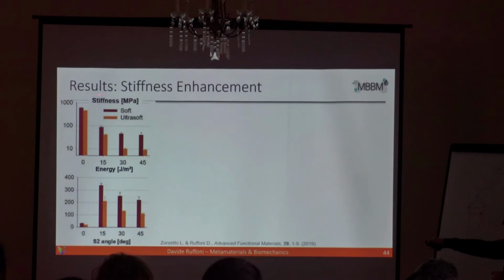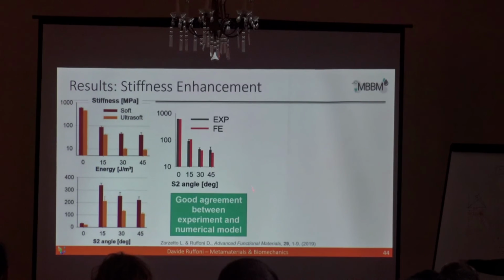So this is how the stiffness of our synthetic cylinders is tuned by changing the fiber winding angle of the main layer. 0 degrees, very stiff, and then 15 degrees, 45 degrees, of course, they get more compliant. This is not a big surprise. And this is the behavior with the soft matrix or ultra soft matrix. This is also how the energy absorption is changing. For stiff cylinders, of course, they are very weak in terms of energy absorption because they fail by buckling because they have straight fibers, and as soon as I introduce some winding angle, I escape this buckling failure and I can absorb more energy before failing. And we did some FE simulation which were quite well in line with the experiments.